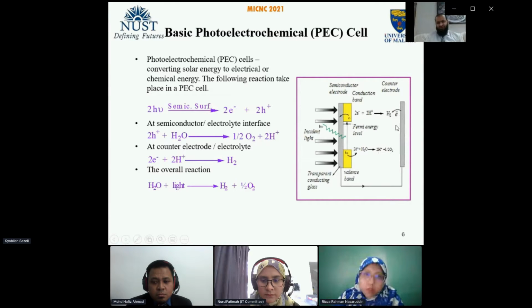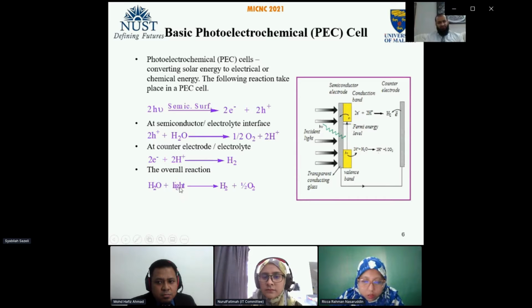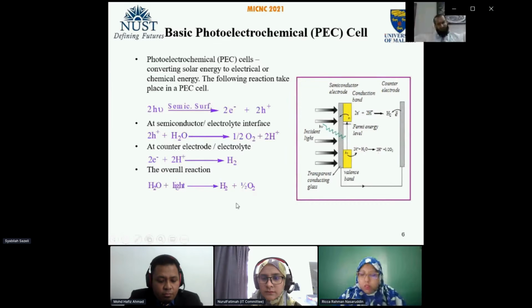Once the proton reaches the counter electrode, it captures the electron, and the reduction of the proton takes place to produce hydrogen gas. So the overall reaction is that light is utilized in the presence of a catalyst, and water is split into hydrogen and oxygen.